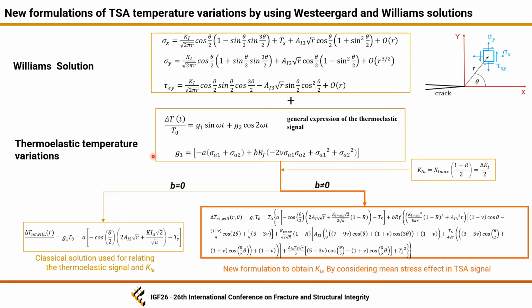The thermoelastic temperature variation clearly, even in this case, depends on the stress ratio and also on the Poisson ratio and the B term that is different from 0. And we have also the classical solution for relating the thermoelastic signal without considering the mean stress effect. Here, this temperature from the classical solution and this one from the new formulation are being used to obtain the synthetic, corrected and non-corrected thermoelastic temperature variation that will be compared with measured thermoelastic data.